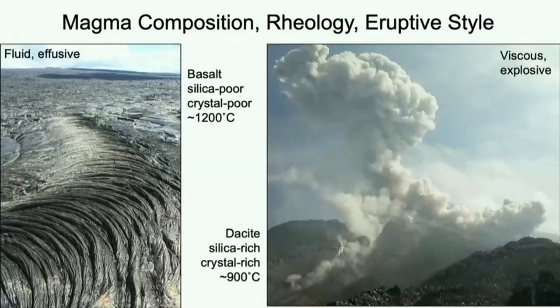So, again, things you probably learned in school. We have silicic lavas that are lower temperature, high silica content, therefore the melt is polymerized. Melts and crystals, the main difference between them is that the crystals have really good short-range order and really good long-range order, whereas the melts only have good short-range order. They're still made of silica tetrahedra, but the long-range order isn't there. They're kind of isotropic on a large scale.